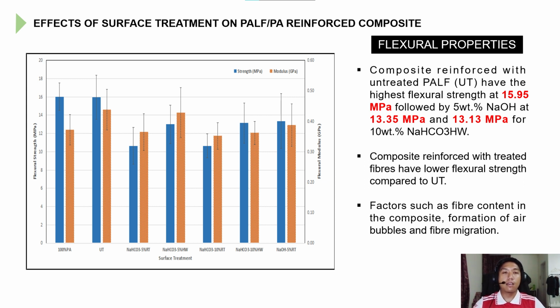this could be due to factors such as air bubbles or fiber migration, where when we fabricated the composites, the fiber and the PA11 sheets are hand laid up using the sandwich method. When we press the mold at the heat press, the fibers tend to shift around in the composite, so we will not have a uniform spread of the fiber in the composite itself. So this could cause, maybe when we cut the composite, some parts may have 3% fiber, some part may have 10%, may have 1% fiber, some parts may even not have any fiber in it at all. So this could be the cause of the result that we have here.